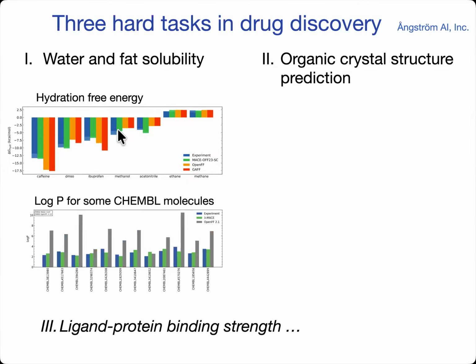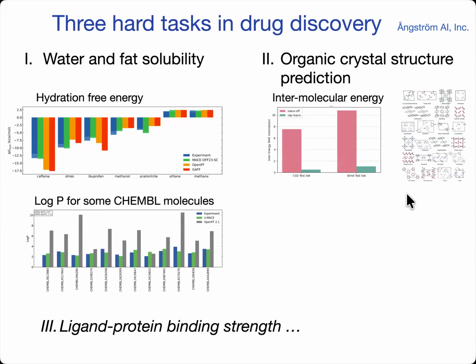And when you go to fat solubility, so typically the way this is measured is the difference between the partition coefficients, the difference between fat solubility and water solubility. The empirical models do much worse. And the MACE model gives you back essentially the experimental result within the error bar of experiment.